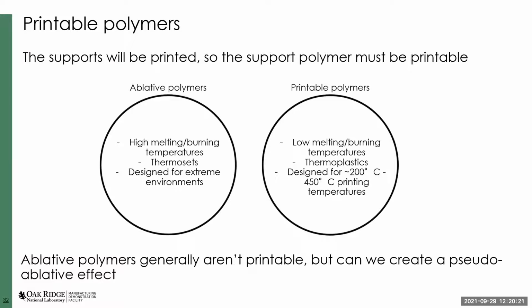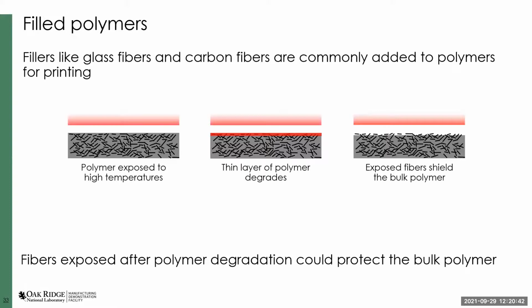So what we needed to do was see if any of the polymers that are readily available for the extrusion printing on our system could act in this ablative manner. We were looking to create a pseudo-ablative effect with a non-traditional ablative polymer, a non-ablative polymer. So we investigated the idea of filled polymers. Several types of polymers printed on large-scale polymer extrusion systems are polymers like ABS that are filled with things like glass fibers and carbon fibers. The reason those were introduced in the first place was because these fibers mitigate a lot of the warping issues seen with larger scale printing. But we hypothesized that by using these polymers as our support structures in the DED process, these fibers would actually protect the bulk polymer from the thermal effects of the DED process.